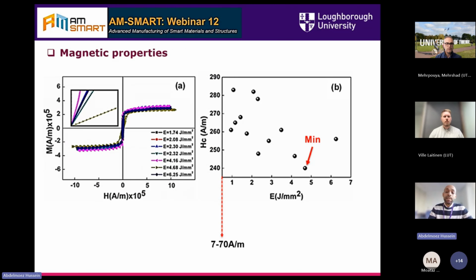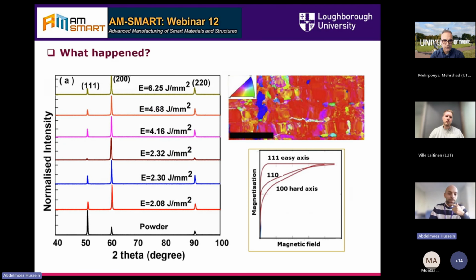We find that even this condition, which has the lowest porosity, has a coercivity of almost 240 ampere per meter, which is way higher than the commercial one, which should be between 7 and 70 ampere per meter. This high difference between the commercial one and the additive manufacturing one should be for a reason. To know what we have, we went for an internal investigation, and we got something interesting from the